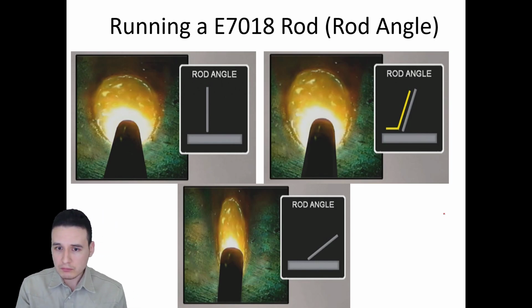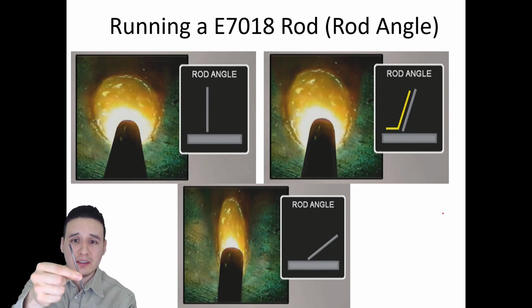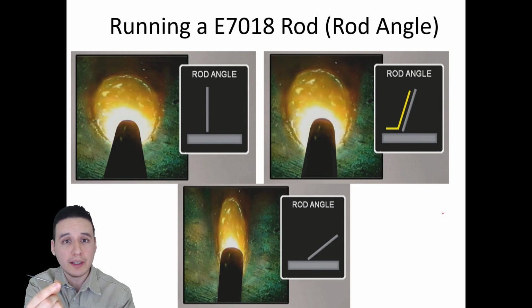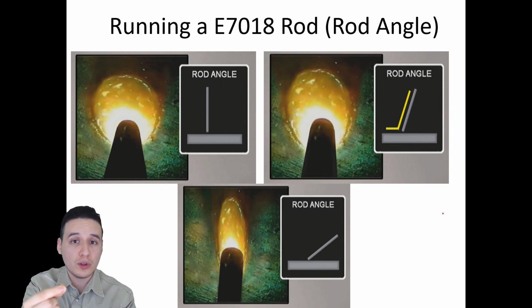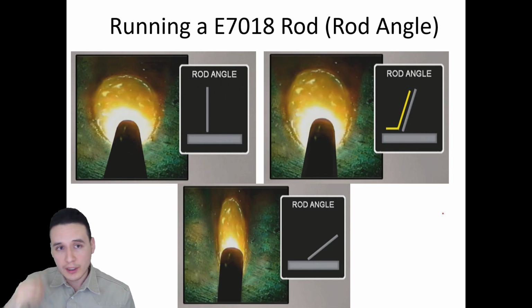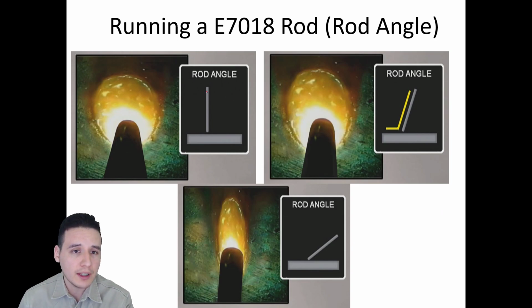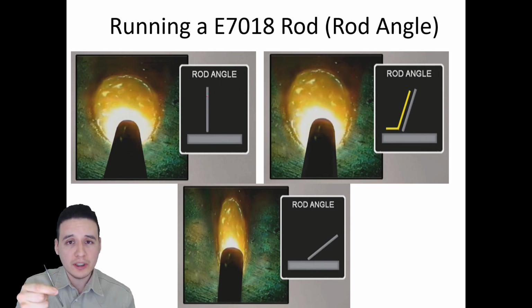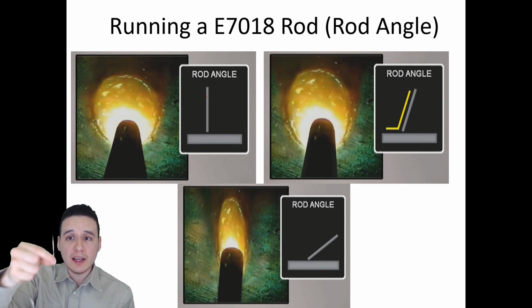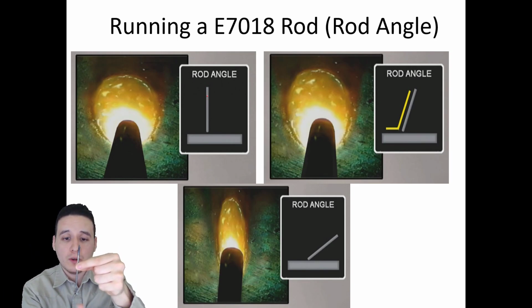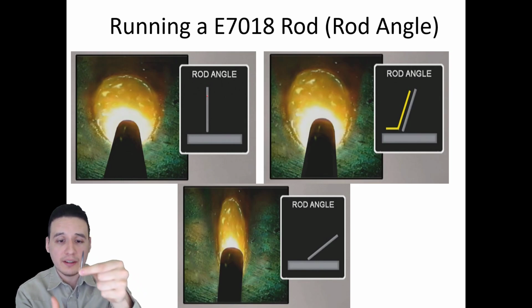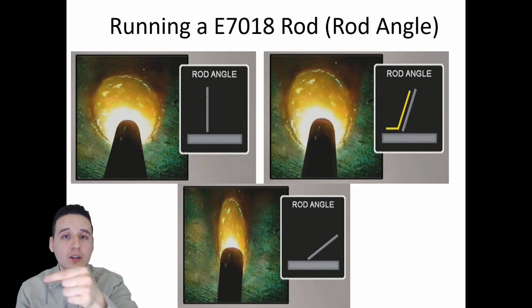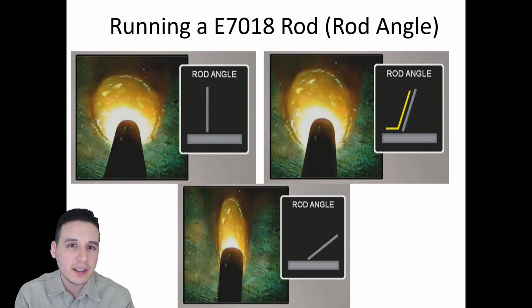Now, you could have a bit of different drag angles, and so we could have a drag angle like this to where it's just barely kind of tilted, or we could have one that's really inclined. The way that you make a decision as to which one is appropriate is, well, depending on what you're trying to do. And so when you have a straight up and down drag angle like they do here, you don't want to have it straight up and down, simply because with stick, as we're welding, we know that this electrode is depositing not only metal but slag as well. And so if that rod is like this, it's going to deposit slag all the way around. Now, the issue with that is that whether we're moving this way or that way, you're going to be running over your own slag, and that's when you tend to get a lot of porosity.